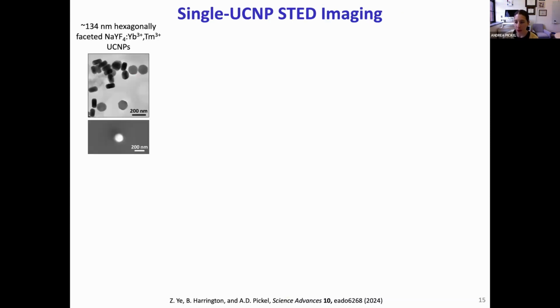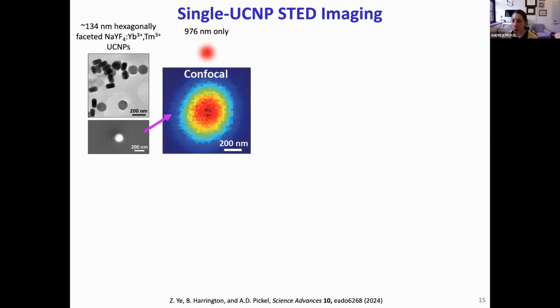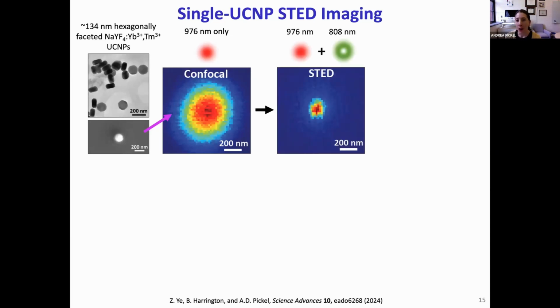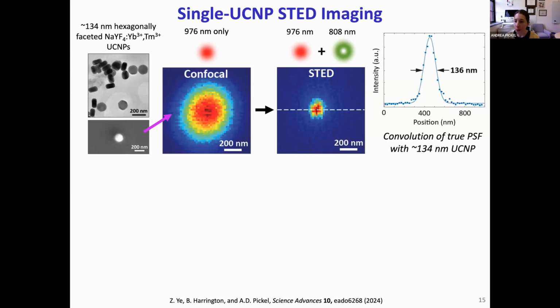To test the imaging performance of our STED microscope, we used individual UCNPs that were approximately 134 nanometers in diameter. This first luminescence image is what we get if we apply only our excitation beam to image a single UCNP. So this is a conventional diffraction-limited image, and therefore, as expected, we get an emission spot with a diameter of several hundred nanometers. But now, if we apply both our excitation and depletion beams, we get a clear improvement, in this case getting a full width at half max of about 136 nanometers.